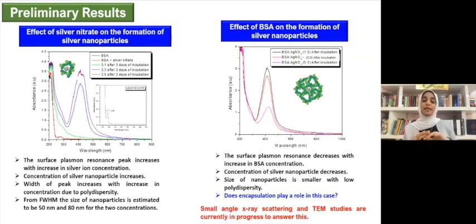Here we observed a completely opposite result trend. As we increased the concentration of our BSA protein, the formation of silver nanoparticles decreased. This was seen by the decrease of the surface plasmon resonance peak. This meant that our concentration of silver nanoparticles decreased, the size potentially also decreased, and now we had a low